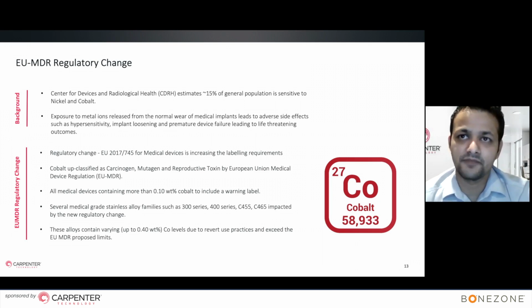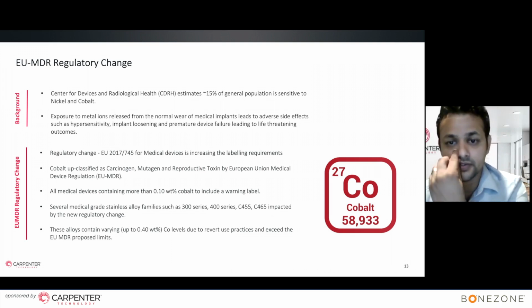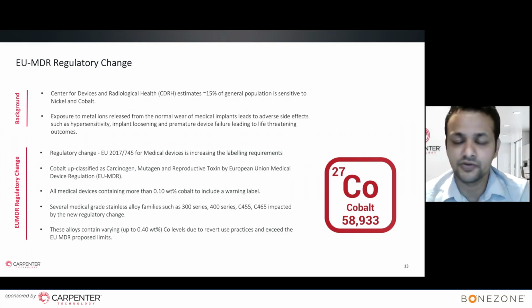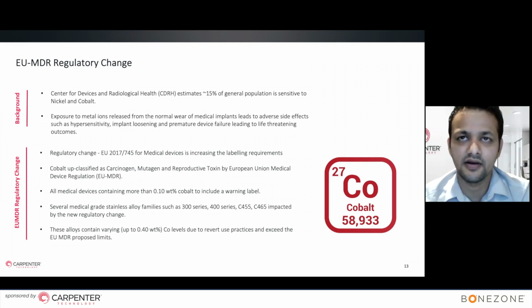And as a result, several stainless steel alloys that were commonly used in the medical device industry, 300 series stainless, 400 series stainless alloys, Custom 465, Custom 455, several of these alloys that have a long history of successful use were impacted because inherently these alloys can contain anywhere up to 0.4% cobalt, just based on the presence of cobalt as an interstitial element during the melt practices, essentially making the majority of the stainless alloys that are used in the medical device industry non-compliant for EU MDR.